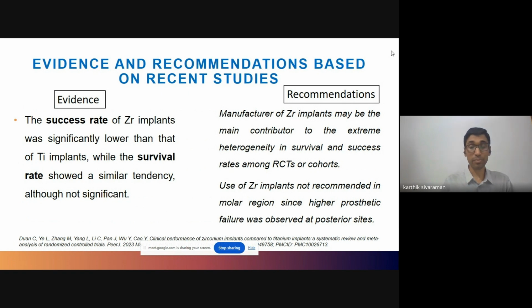And that brings us to the original point, the point which I mentioned before, that when you are using an implant, whether it's in this case zirconia, we need to ensure that the manufacturer has an established R&D process on the methodology and has data on the performance of the implant. Now, this study also observed that the zirconia implants had higher failures or prosthetic failures, especially in the posterior region. So they recommended that the zirconia implants not be used in the molar region.